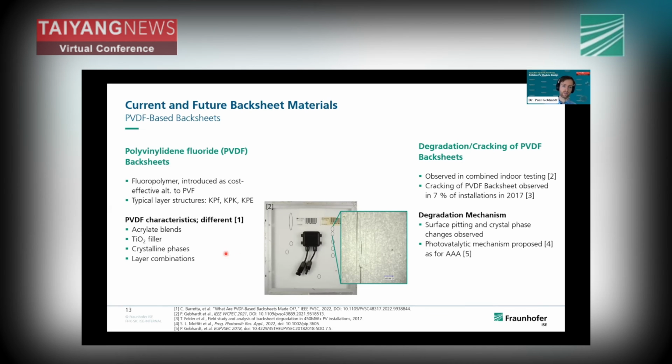They can be, so the outer layer is usually PVDF, but the inner layer can be a fluoropolymeric coating. It can be PVDF just as well, or it can be some PE layers or some POE or EVA blend or some similar material.